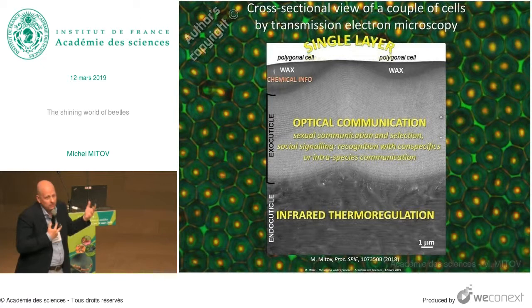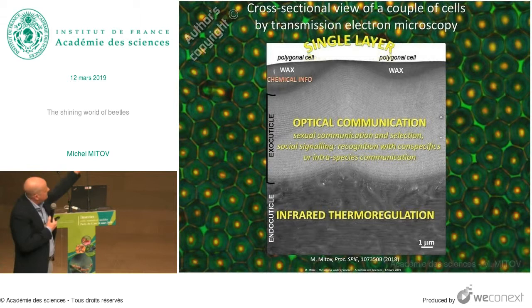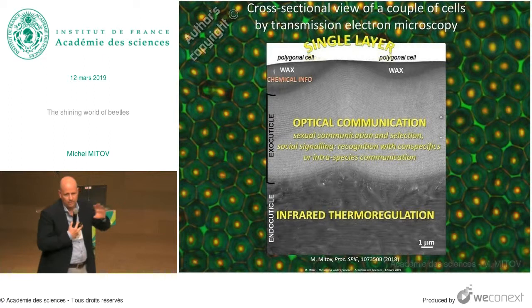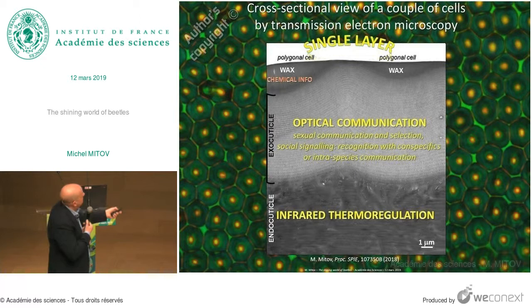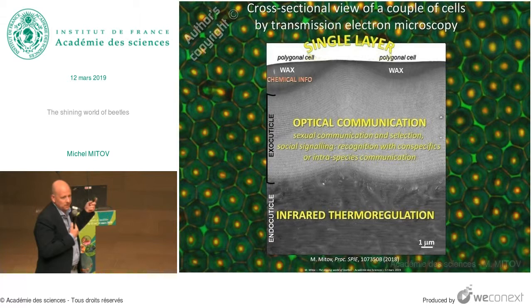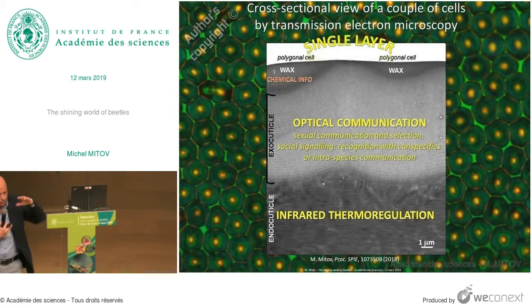As you know, there are many insects and beetles which have tessellated carapaces. For the lowest part of the cuticle — as with lobsters, for example — there are fewer minerals because the cuticle does not need to be as resistant to shock, and the pitch in that part is in the infrared, so perhaps we can talk about infrared thermoregulation. And within a single layer it is very interesting to note that to adapt with evolutionary pressure, you only need to tune the pitch rather than change materials with different optical indices.